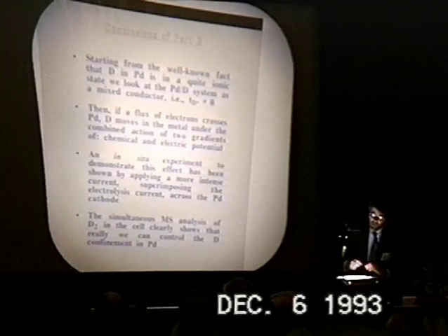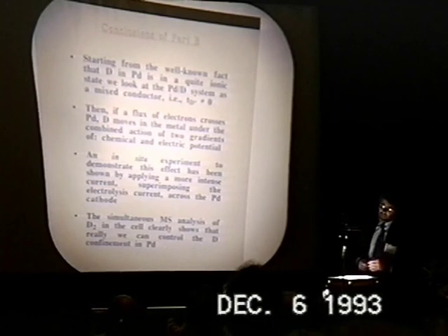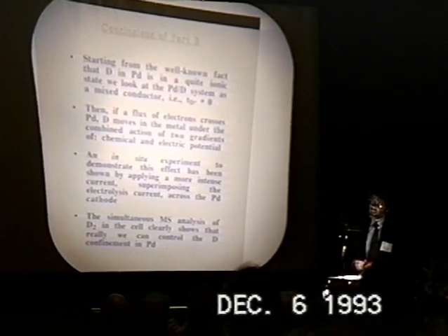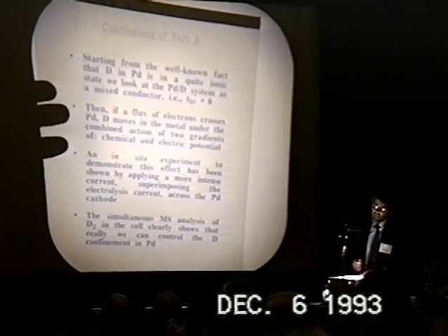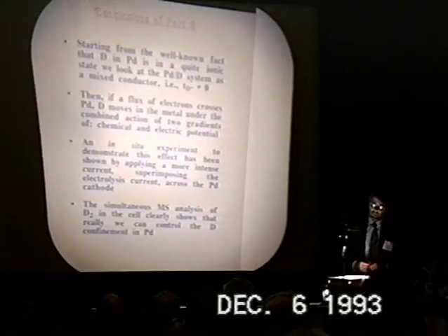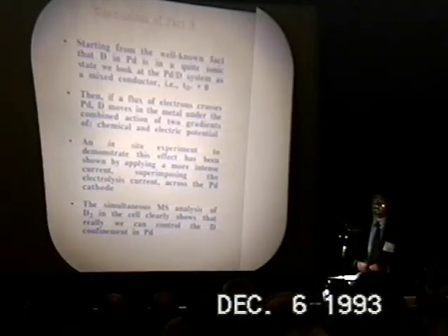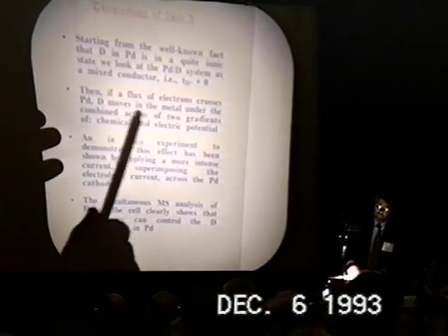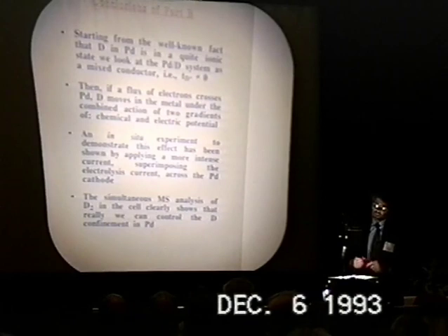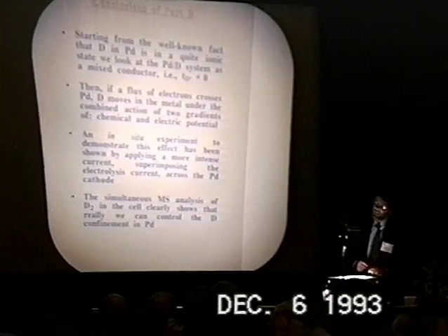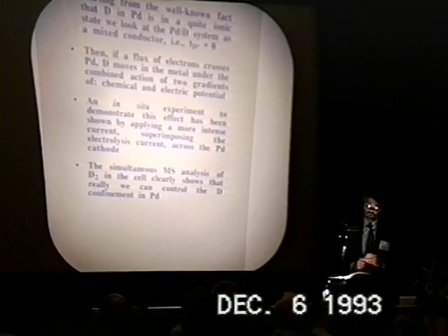So the partial conclusions of this part are, starting from the well-known fact that deuterium in palladium is in a quite ionic state, we look at the PdD system as a mixed conductor, that is, with an ionic transport different from zero. Then, if a flux of electrons crosses palladium, deuterium moves in the metal under the combined action of two gradients, chemical and electric potential. And in an in situ experiment, we demonstrated this effect, as we showed, applying a more intense current, superimposing the electrolysis current across the palladium cathode.